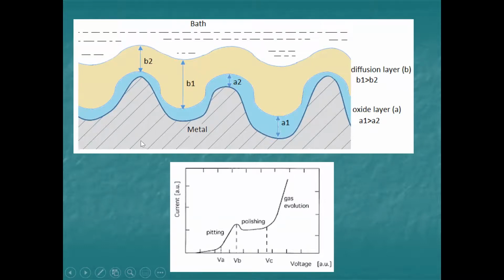And since we're normally electropolishing a metal which has a passive film on it, such as stainless steel or aluminium or titanium for that matter, you can electropolish any of these, then there's always going to be an oxide layer on the surface as well. And this oxide layer is going to grow because we are making this anodic. And as you know, when you make something anodic, there is a tendency for the oxide film to grow. We covered this previously. If you look at the current voltage curve, it's going to look a bit like this. Imagine this is stainless steel. If you drive it in the anodic direction, you're going to start getting pitting formed if you hold the potential between here and here. And what we actually want to do in stainless steel, we want to put it into the passive region. So we need to polarize it sufficiently to get into that region.